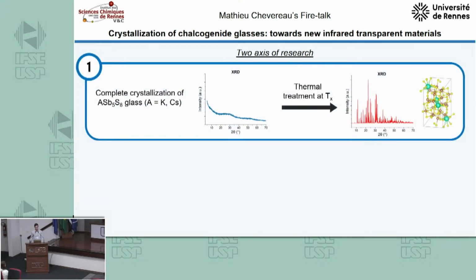So with that context, let me dive into my subject. I have two main axes of research. The first one is the most novel one, which is the complete crystallization of Sb5S8 glass. The goal is to make a glass whose composition matches the crystalline phase. First you make the glass, and then you make it crystallize fully to obtain an infrared transparent ceramic. This would be the final goal.